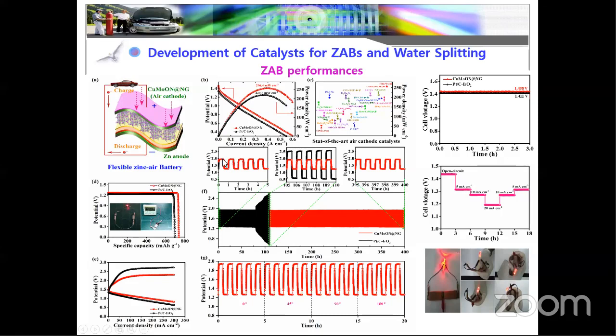You can see the anodic sites and the cathodic sites are almost stable, because the round trip efficiency between the anodic and cathodic is maximally stable compared to the conventional cathodic catalyst. With the conventional cathodic catalyst, you can see the potential goes toward almost 2.5 in the OER part. It is not stable, and it also dropped to less than 0.6, because an air cathode should maintain this kind of potential reversibility. For ours the potential is almost near 1.2, which is good compared to the other catalysts. From the studies, our catalyst is highly durable, and the gap between charging and discharging, the charging potential gap, is very low compared to the conventional.